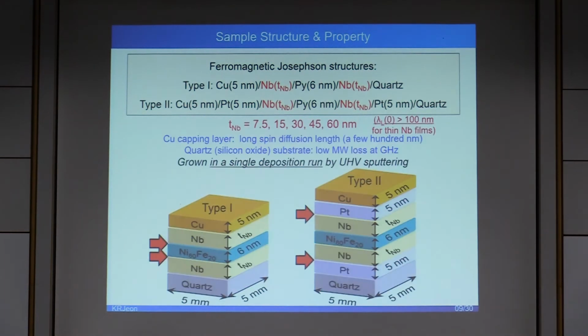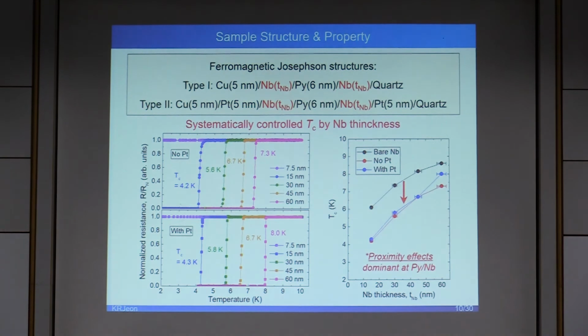In our symmetric sample structure, spin pumping across the permalloy-niobium double interface above and below improves the sensitivity of magnetization dynamics to the spin transport in the superconductors. In addition, the superconducting transition temperature, which was systematically controlled by the niobium thickness, enables us to explicitly investigate the effect of superconducting correlation on the spin pumping and transport properties.